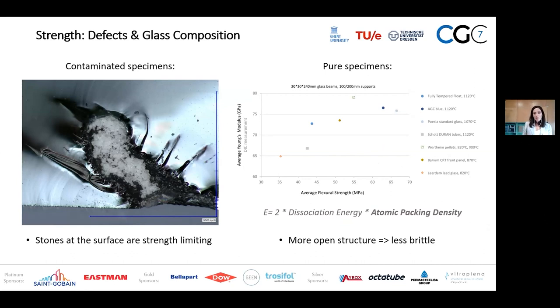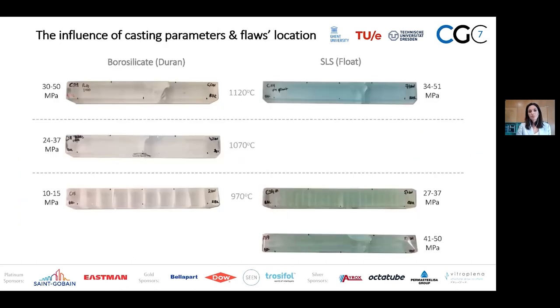And why is that? Because we realized that some glasses with a very strong atomic bond, but a lower atomic packing density, had more space around the flaw to deform, and then eventually they would fail at much higher stress. And we also saw how critical the casting temperature can be. So of course, the higher the temperature, the more homogeneous and the stronger the component will be.